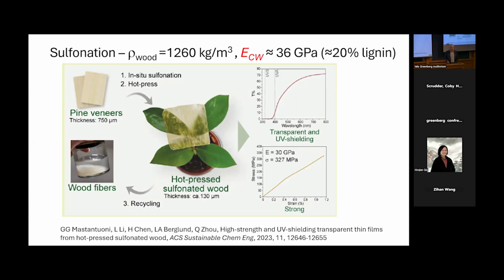I will go through a couple of chemical treatments that we've been using. Sulfonation has been of interest because if you want to use ion conductivity, then sulfonation provides such mechanisms. In this case, we were able to get a density of 1260 kilos per cubic meter, and then the cell wall modulus is 36 gigapascal. We're utilizing the realization in previous work by Bing that if you keep the lignin there, you have a resin which is intrinsic to your material. At that stage, you can get something like 36 gigapascal.